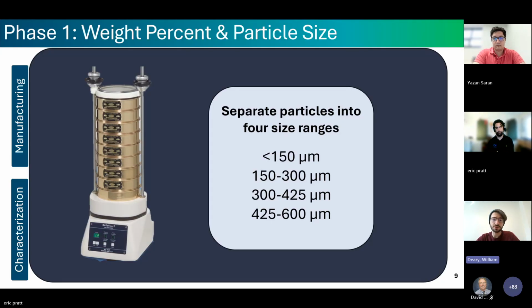It was surprisingly difficult to get a usable amount of cross-linked polyethylene in the less than 150 micron range, because at that size, the electrostatic forces, which are so prevalent in plastic, keep our powdery material clumped together, and they made sieving a challenge. This was important to note because any processing challenges that we encountered at the lab scale would likely become an even greater challenge at the industrial scale.